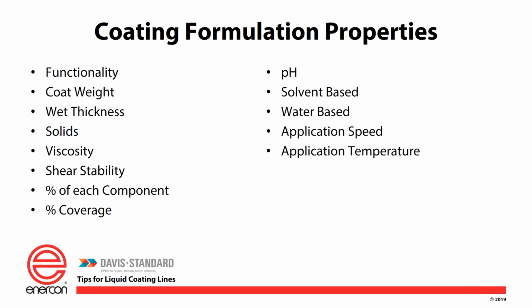It'll be like a chrome, rubber, chrome. And each roll runs at a different speed. So this nip impression in between the two and the difference in speeds create a shearing action. And what this does is it lowers the amount of coating at each nip as you go up, and also will make it flow out onto your sheets. It's actually shear thinning the coatings and gives it a better wettability on the substrates we're going to be applying it to. And then we want to know what's the percentage of each component.